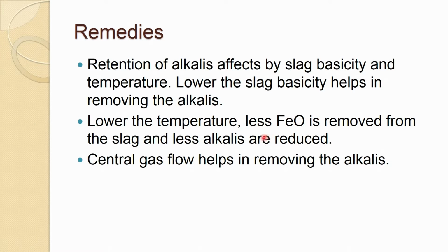So, you are losing more FeO with the slag. On the other hand, the alkalis are not that much reduced. So, they go with the slag and they can be removed. So, again an optimum or compromise has to be made between these two. However, when alkali content has increased, probably at that time you may go for a less FeO removal, because you want to remove that, and then again you can resume the normal operation of the blast furnace.